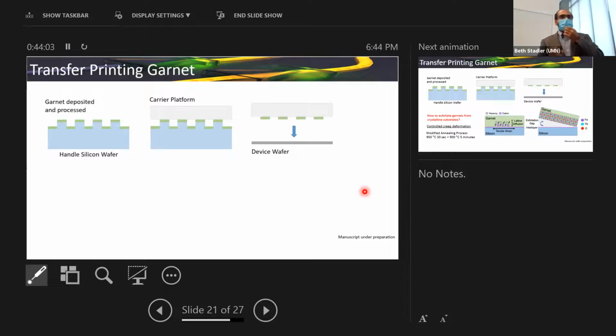So one of the problems that you might have noticed already in the discussion so far is that garnets have to be annealed at a very high temperature, around 900 degrees Celsius, right after you sputter them, or even sometimes pulse laser deposit them, in order to actually crystallize and benefit from the Faraday rotation that it has to offer. So something that we were thinking about was, why not, just like a lot of other materials that are developed for a variety of transistor applications or even other optical applications, is there a way to transfer print garnets? And we started exploring that idea.